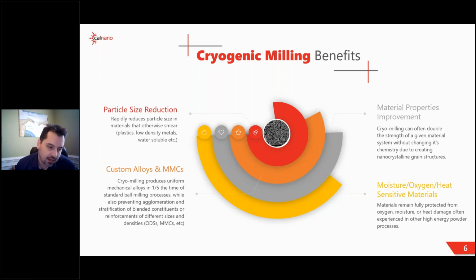So in the same way that a forged variant of a given material will be better in mechanical properties than a cast version, or a heat-treated version of a steel having a finer crystal structure will have a harder and stronger mechanical property than its annealed or large grain counterpart, we can take that same Hall-Petch relationship and extrapolate it and control the microstructure to a much finer degree. So it essentially adds new tuning knobs to every given material because we can now control the microstructure at a much finer level than ever before.